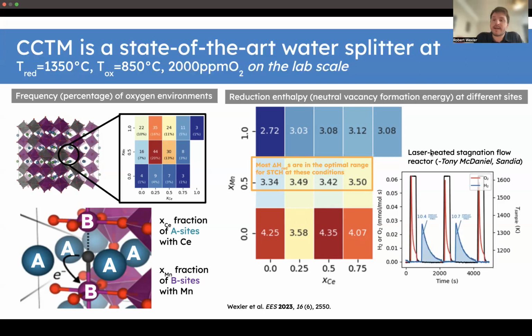Laser heated stagnation flow reactor measurements done by Tony McDaniel at Sandia show that when you reduce the material, here you can see in black, heating the material from about 1123 Kelvin to 1623, which is 850 and 1350 degrees Celsius, that causes a loss of oxygen in the material, which upon cooling and introduction of steam leads to the production of hydrogen in quantities of 10.4 and 10.7 mL per gram for the first 2 cycles.